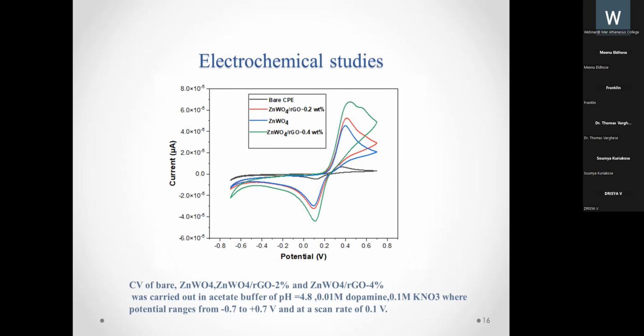In addition to that, 0.1 molar KNO3 is used as a supporting electrolyte, and the potential window ranges from -0.7 to +0.7 volt, and it is done at a scan rate of 0.1.